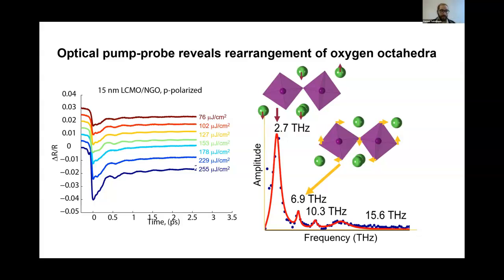So not only does the manganese oxygen bond angle favor or disfavor charge ordering, but destroying the charge ordering will impulsively change that bond angle. And finally, this 15.6 terahertz mode, this broad mode here, is a Jahn-Teller mode. So this is basically a coherent oscillation of the Jahn-Teller distortion in the manganites. And this is all consistent with literature. So we're not the first people to publish this. Andrea Cavallari and Simon Wall and many others have seen these coherent phonons in manganites. So now we need to understand what's going on in the first few picoseconds of the photo switching phase.